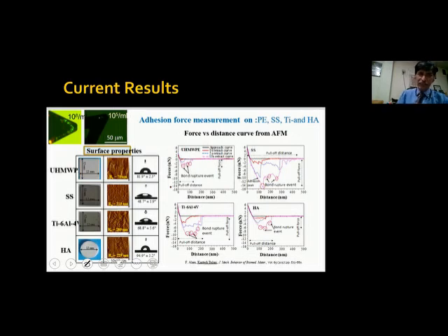And here we take this AFM tip, we attach a bacteria using some glue. That's a separate process in itself. And then we have tested various surfaces like polymeric, stainless steel, titanium, hydroxyapatite, and we'll see the de-adhesion force. So we bring this tip closer to the substrate, hold it for 0 seconds, then retract it, 5 seconds, retract it, and 10 seconds, retract it. Now let me take you to a curve. Select, say, for example, this. For 0 seconds, you will see there is some de-adhesion force, the red curve. If I hold the bacteria in contact with the substrate for a longer time of 5 seconds, I can see the adhesion force is increased. If I keep it for 10 seconds, it is further increased. Not only that, the distance or the length of protein which is attached also increases. For 0 seconds it was some, for blue it became higher, and then for 10 seconds it became even higher, right?